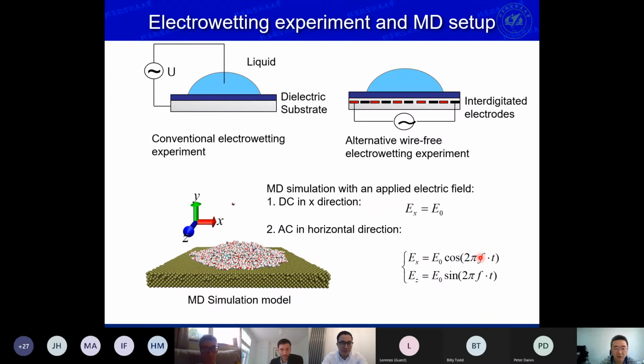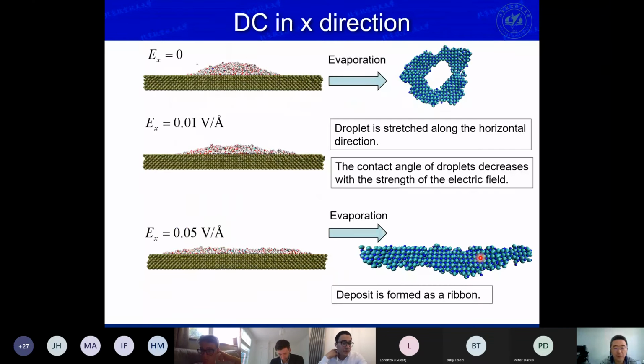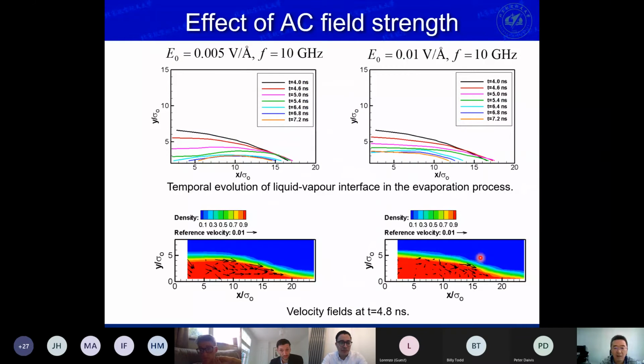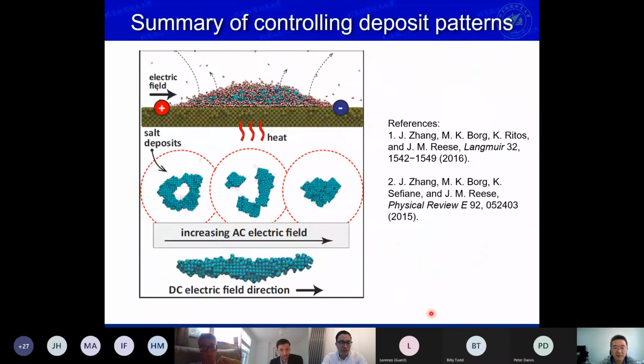And we use MD to explain how the phenomenon is formed, and then we use the electric field to control the patterns. Because of the time, I just use this one to conclude what we have found. If we use an AC electric field, we can change the ring-like pattern to a clump. If we use a DC electric field, we can change it to a ribbon. And this is how we use electrowetting to control the patterns.